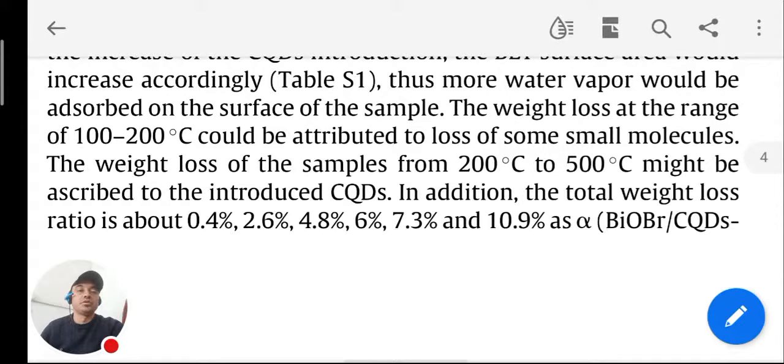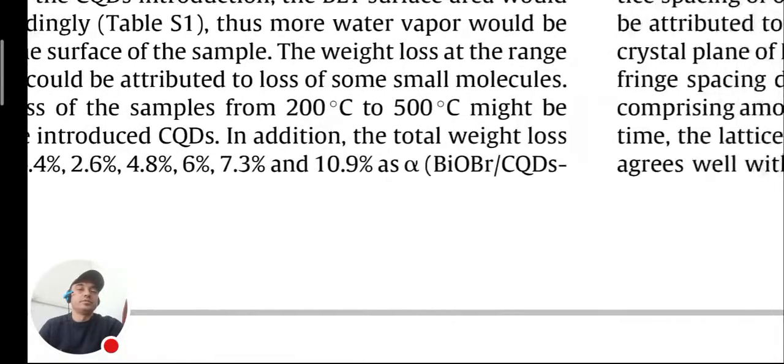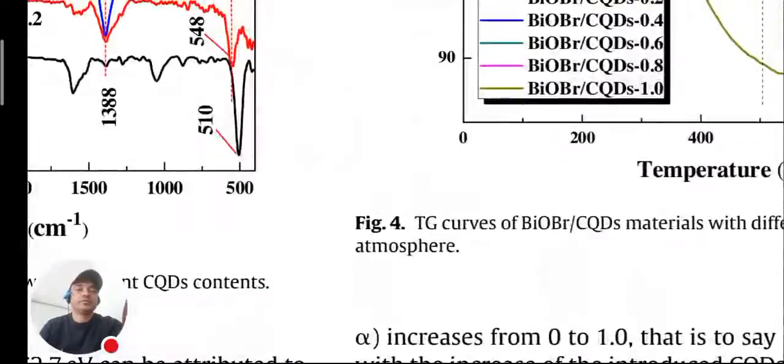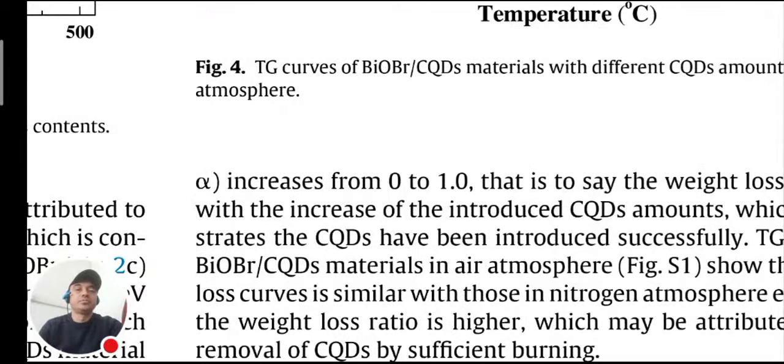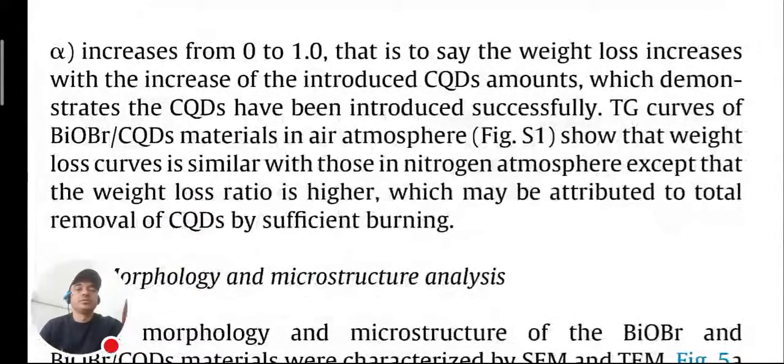In addition, the total weight loss ratios are 0.4%, 2.6%, 4.8%, 6%, 7.3% and 10.9% for BiOBr carbon quantum dots with content increasing from 0 to 1.0, and the weight loss increases with the increase of the introduced carbon quantum dots amount, which demonstrates the carbon quantum dots have been introduced successfully.